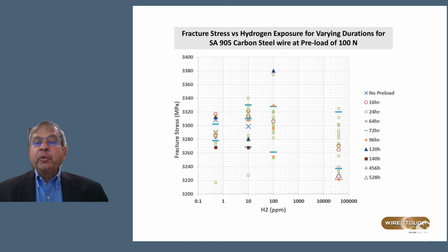Then we've also done, with the help of Oak Ridge National Lab, some testing on the wires that are used. Wires are not exposed to hydrogen, but because there could be some low concentration levels of hydrogen in the environment surrounding the vessel, it is important to document how the wires would perform under those conditions. In extensive testing of the wire at different stress levels and at different hydrogen concentration levels measured in parts per million by weight, we do not see very significant effects on the strength of the wire. So for all practical purposes for design, we can assume that the steel wires that are made out of very high strength steel are in fact not as susceptible to hydrogen.